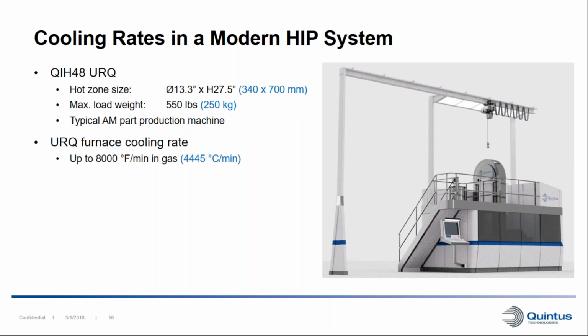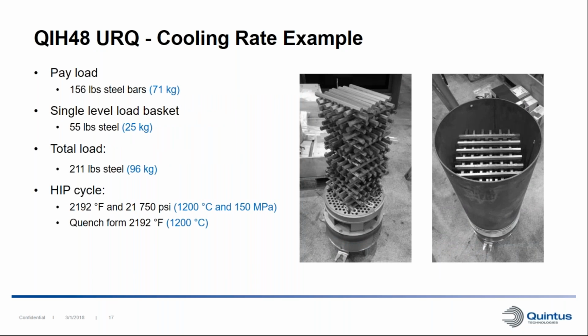In this kind of system, we can actually achieve up to 8,000 Fahrenheit per minute, which is very fast. And I will give you a real case example of this here. For this case, we have a payload of steel bars that we can see stacked like this. They weigh 156 pounds altogether. We have a single level load basket, also in steel, weighing in at 55 pounds. So we have a total load of 211 pounds of steel that we're going to process.